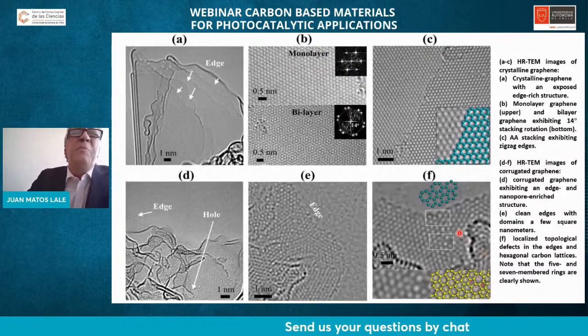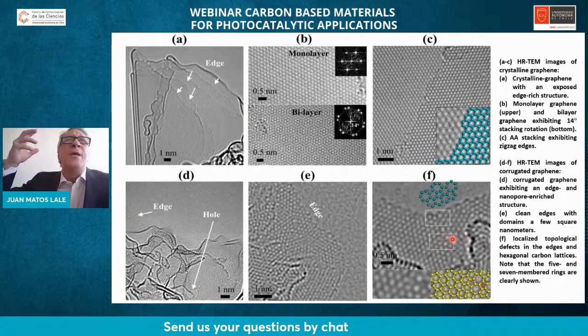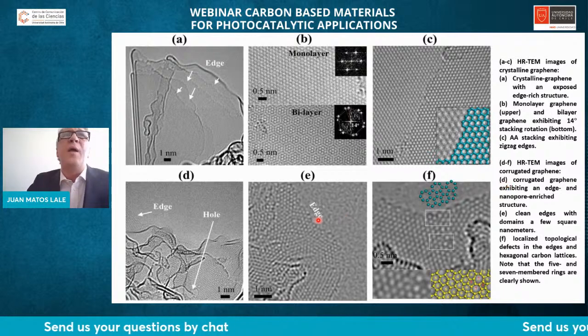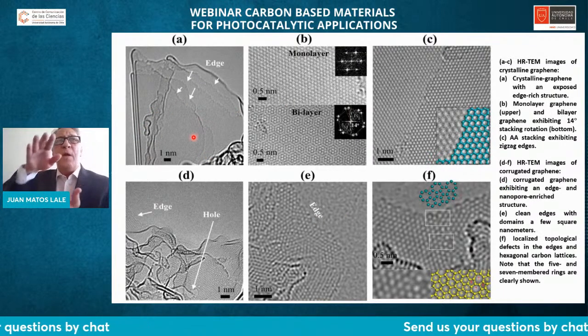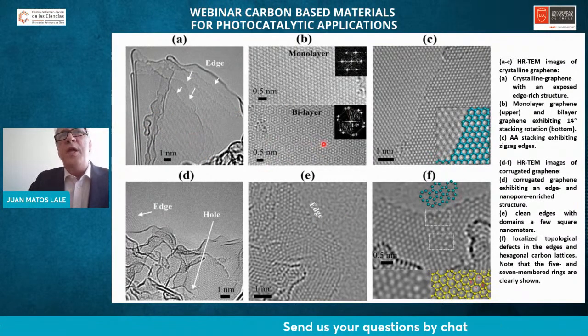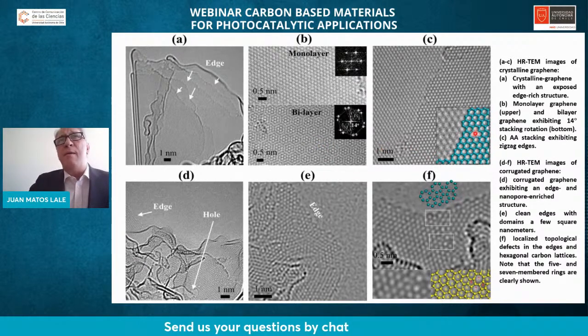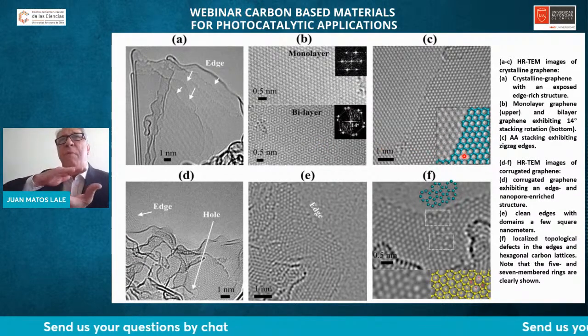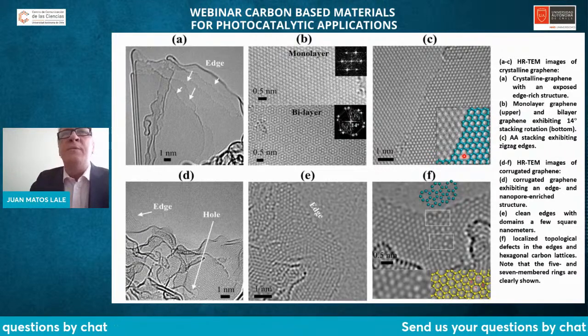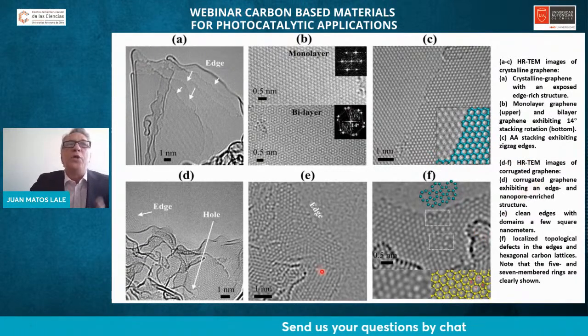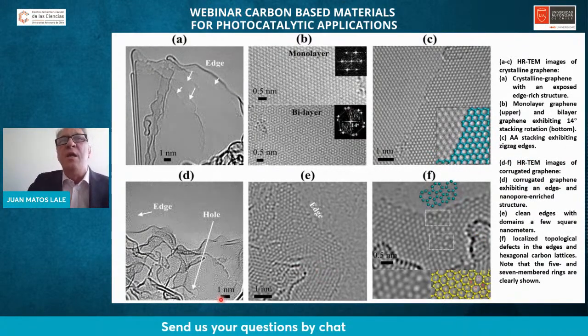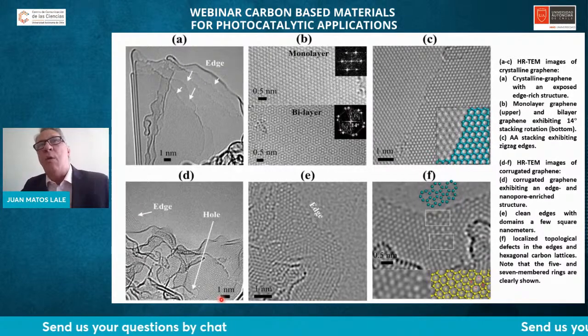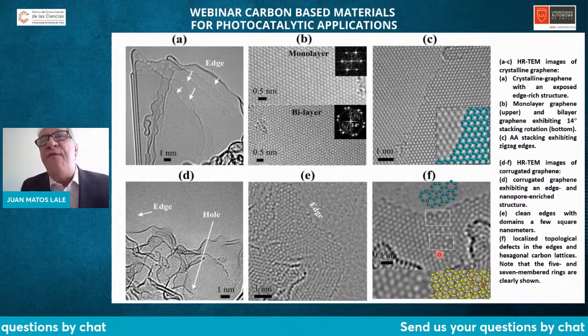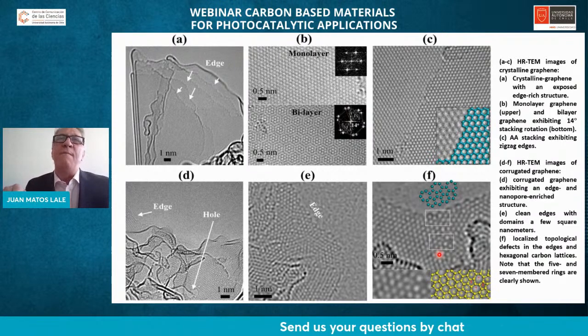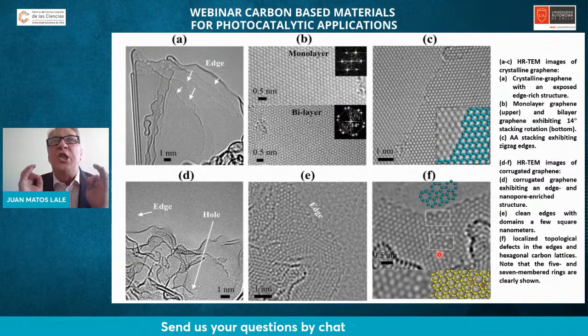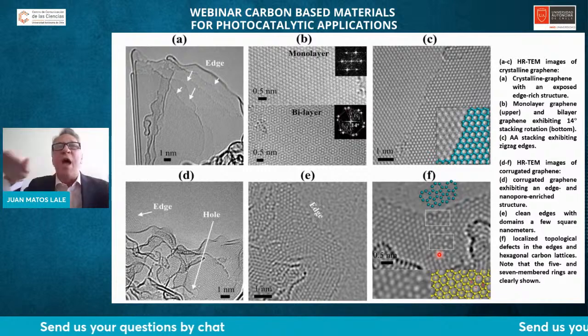This kind of nanostructured carbon material is very useful, because we are able to control the topology. In a very well-ordered graphene, when we reconstruct the topology, we are able to see that all the graphene layers are very well established with rings of six carbon atoms. But when we are in presence of corrugated or very highly distorted graphene, we are able to introduce defects. The defects are very important in photocatalysts because they introduce changes in the electronic density of the graphene layers.